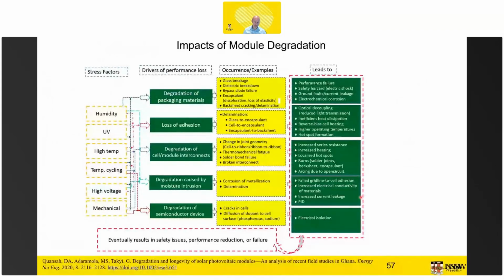So the final part is how can we really use this work that I showed earlier. What we do mainly in the lab, how can we translate that to the field? And then it becomes a bit more complicated, because even these great tests that labs like NREL present are typically only one stress factor, but outside the module sees all these stress factors at the same time, and they interact. Typically, they can either make the impact worse, or they can mitigate the impact. PID is a good example that can be mitigated by UV, which is good, but in most cases they really accelerate each other.